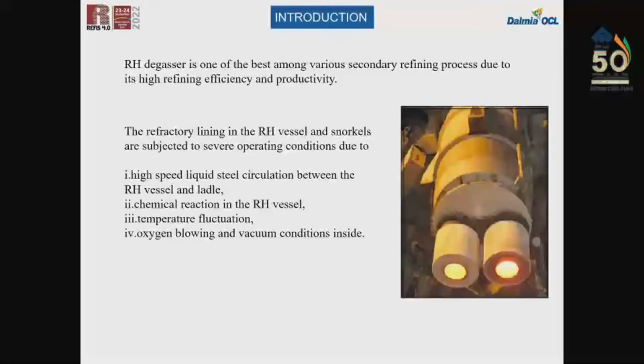Here is an RH Degasser, which we all know is one of the best and most preferred secondary refining processes, used for productivity and efficiency. But all the refractories used in the RH degassers and in the snorkels are subjected to very severe conditions like the high speed circulation of liquid steel, the chemical reaction in the RH vessels, the temperature fluctuation, as well as the oxygen blowing and the vacuum condition inside the vessel.